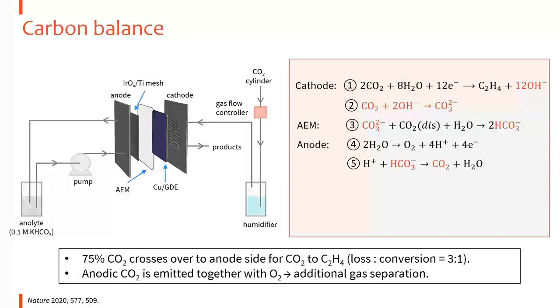And more seriously, there is another challenge from the carbonate, because the carbonate will cross the membrane and reach the anode side. At the anode side, we have the OER reaction for water splitting, but at the same time we generate protons, and protons react with carbonate and bicarbonate so that it releases CO2. That means if we feed all the CO2 here, we expect that all the CO2 will become product, but the reality is that the CO2 will not only be converted into product, but also cross over the membrane to the anode side and be emitted together with oxygen.